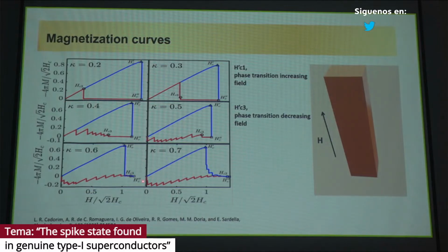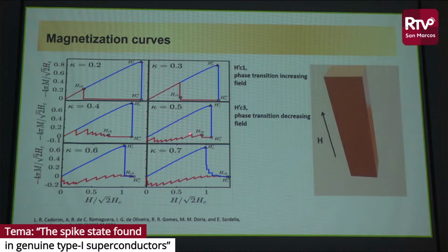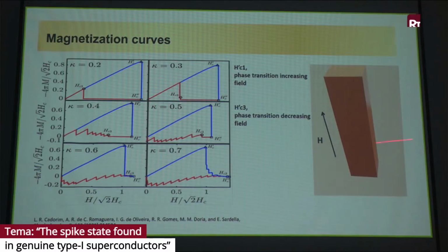So we have here the usual diamagnetic behavior, but in this case, the paramagnetic behavior. Similarly, when decreasing the values of kappa, we can see diamagnetic, paramagnetic, diamagnetic. Sometimes it is both diamagnetic and paramagnetic, but in this case we decide that it's paramagnetic because of the measure of the magnetization. So we can divide that region of the intermediate type 1 superconductor into diamagnetic and paramagnetic regions.